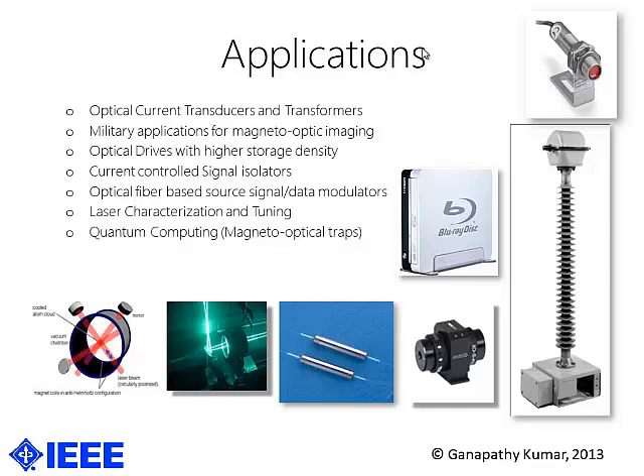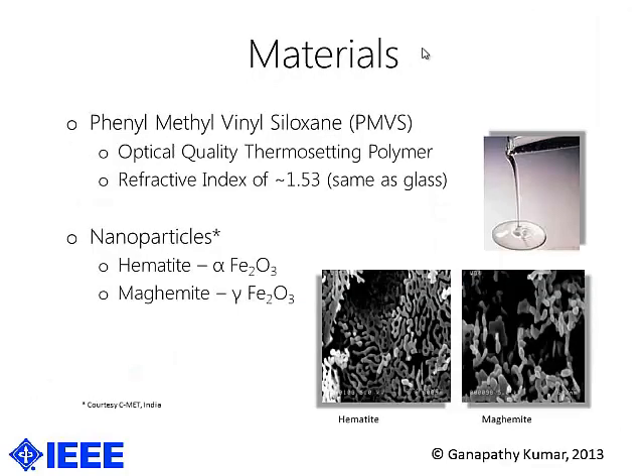can develop magneto-optical traps. So the materials that we chose for this particular study, we used a thermosetting polymer, phenyl methyl vinyl siloxane, poly-phenyl methyl vinyl siloxane, and this is an optical quality thermosetting polymer with a refractive index of 1.53, close to glass. And for the nanoparticles, because we're developing a magneto-optic sensor, we wanted to go with some composite of iron oxide, some compound of iron. So we decided to go with hematite and maghemite. They both have ferromagnetic and ferrimagnetic characteristics, but that will not be focused in the scope of this presentation.